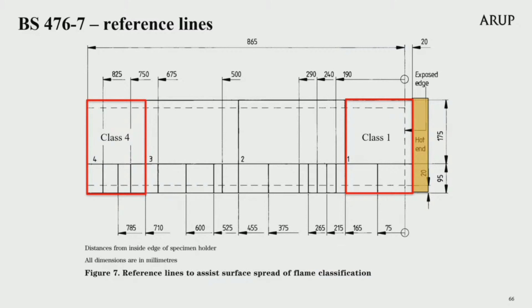The Part 7 standard sets out how the exposed face of each specimen shall be marked in detail on its surface, with a reference line along its length and 95 millimetres above its bottom edge. To assist in the observation of flame travel, the specimen shall be marked at intervals along its length with lines normal to the reference line and at intervals shown in Figure 7 of the standard, which is on screen now. The 4 vertical lines that run full height are the classification limit distances along the sample for Class 1, Class 2, Class 3 and Class 4.